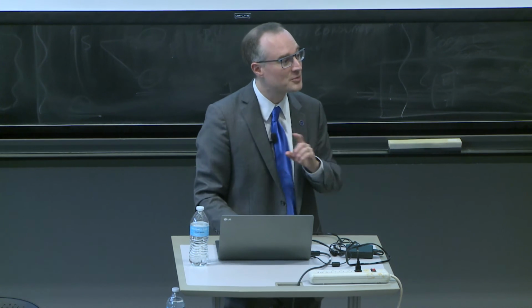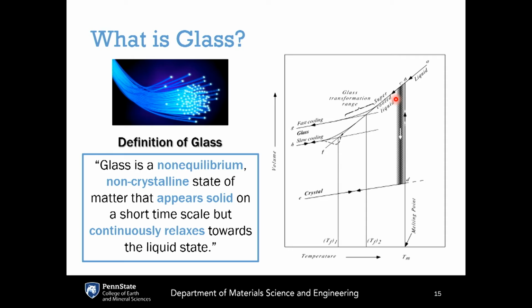So if you take a liquid that's difficult to crystallize and you cool it fast enough through this regime where it's likely to crystallize, you cool it so fast, the atoms simply don't have time to keep up. Then you get what is called a supercooled liquid.